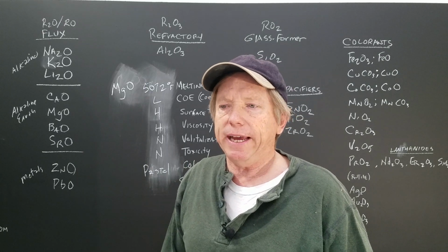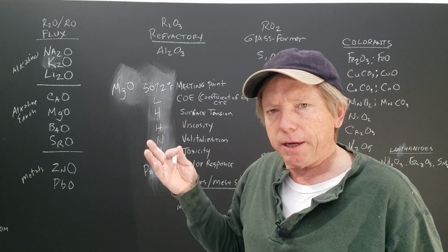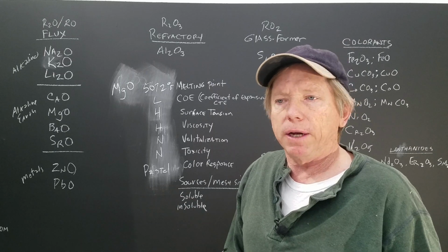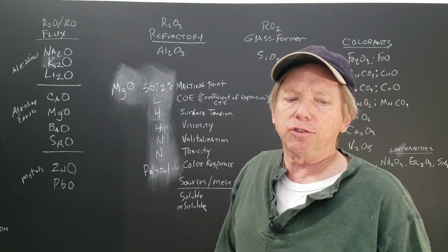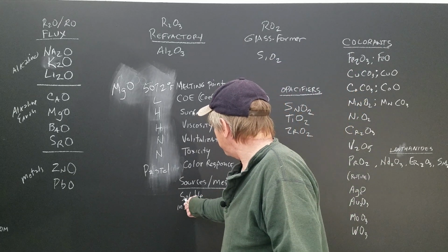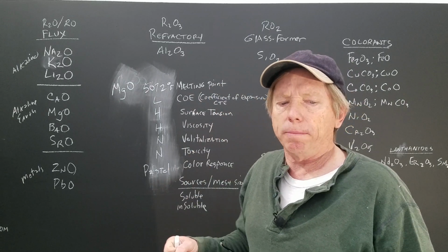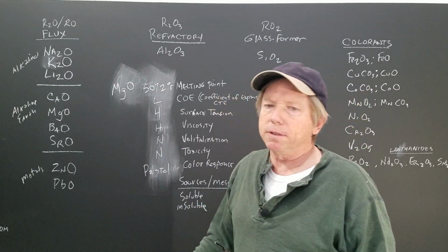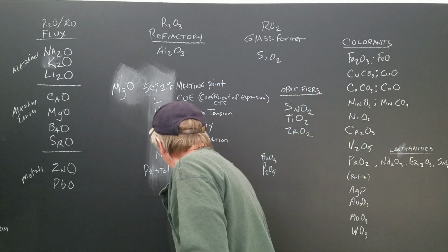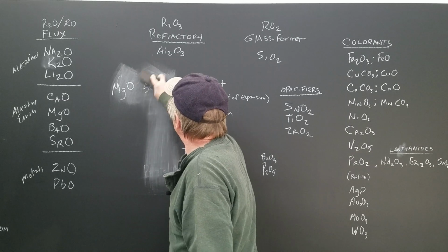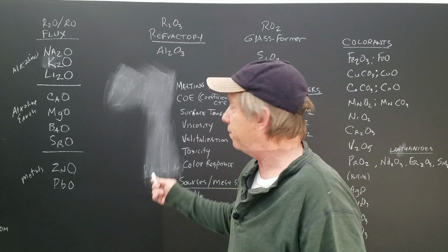It's not always the case. If you have a lot of magnesium or just a little, then you may not get mattes from it. It may help in the melting, but this is generally what people say about magnesium: pastel matte surfaces. All right, so the sources are going to be talc, dolomite, and magnesium carbonate. The soluble source would be Epsom salts, but you really don't use that in glazes. Val Cushing used to love dolomite, magnesium glazes, so a lot of his glazes are in this category.